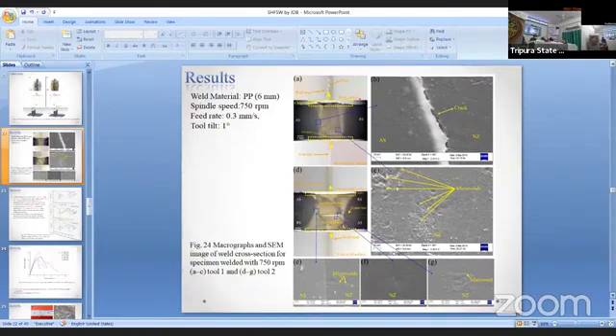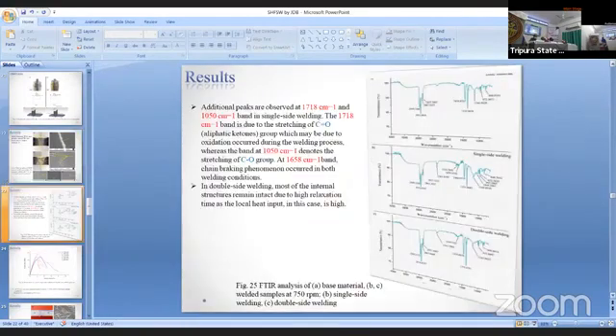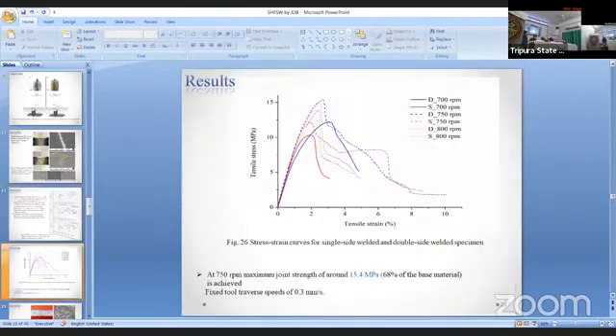So we again thought of developing, and moreover, if we talk about the FTIR analysis, it can be seen that at the 1,658 centimeter band, a chain breaking phenomenon occurred. That is one of the reasons why the voids or the cracks took place. And in the case of double-sided welding, most of the internal structures remain intact due to high relaxation time, as the local heat input in this case is high in comparison to the conventional welding process.